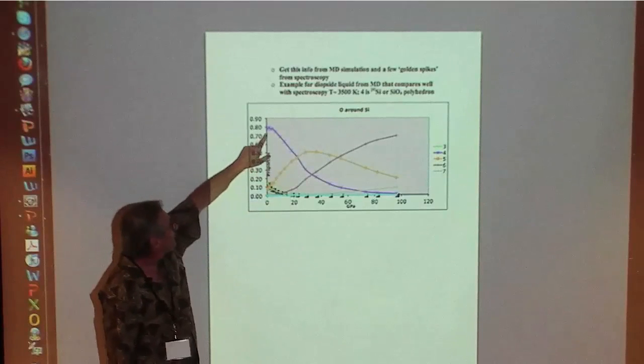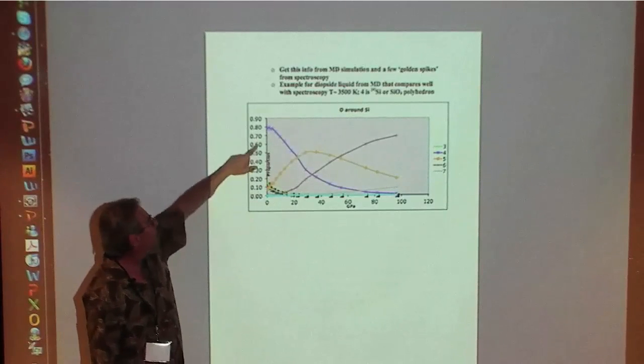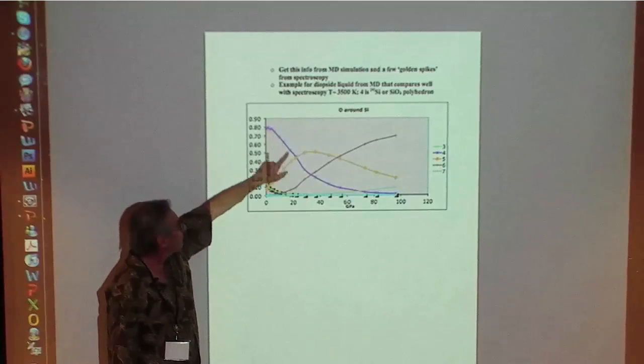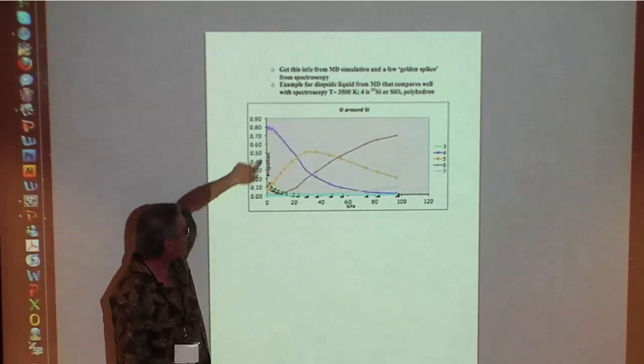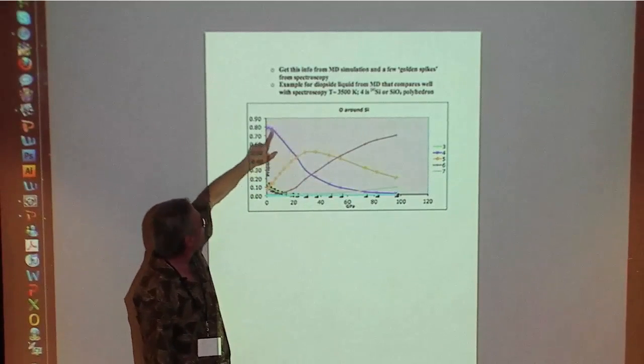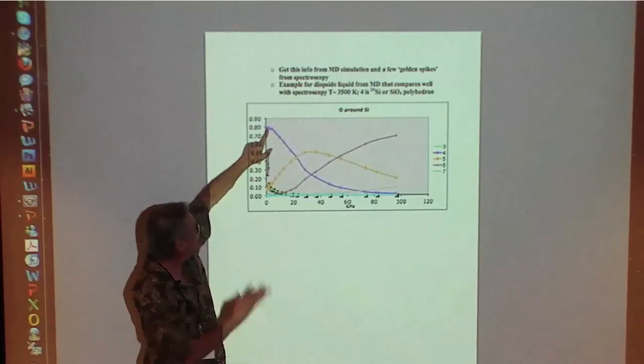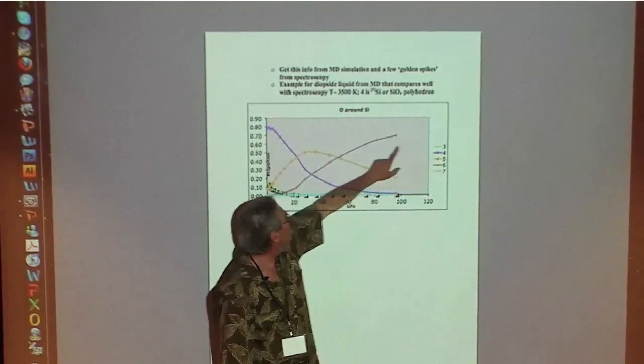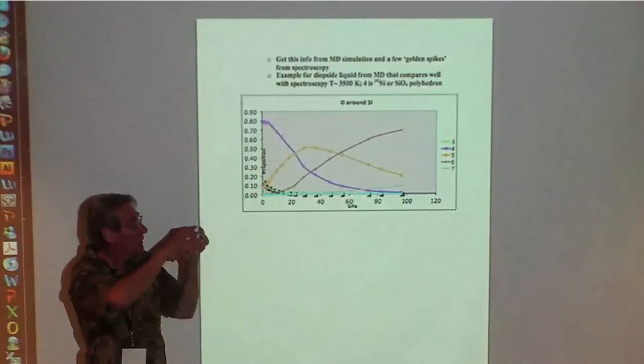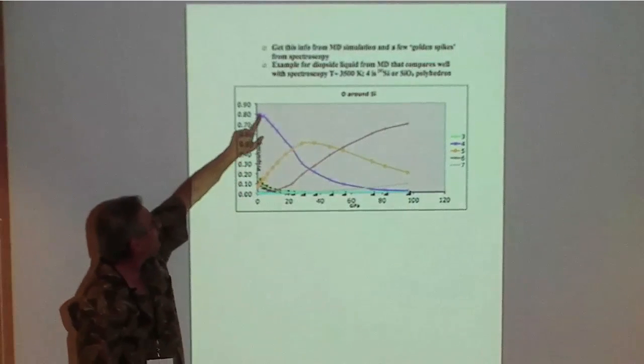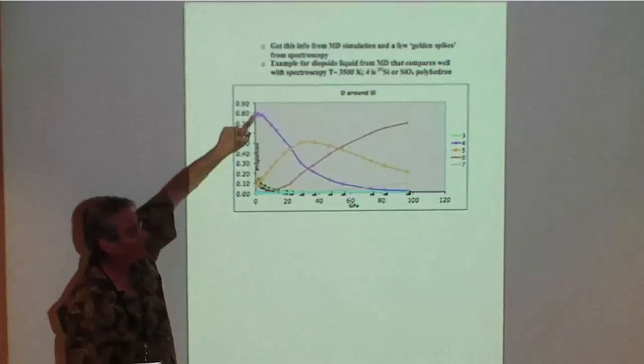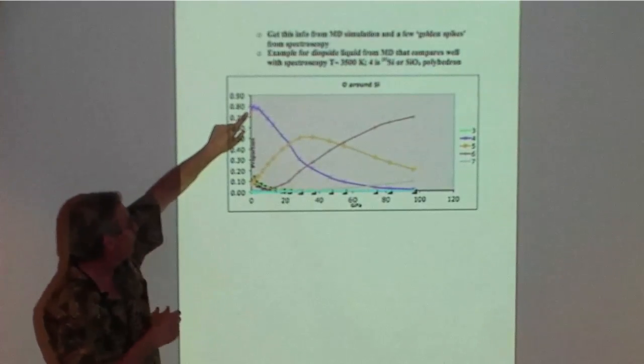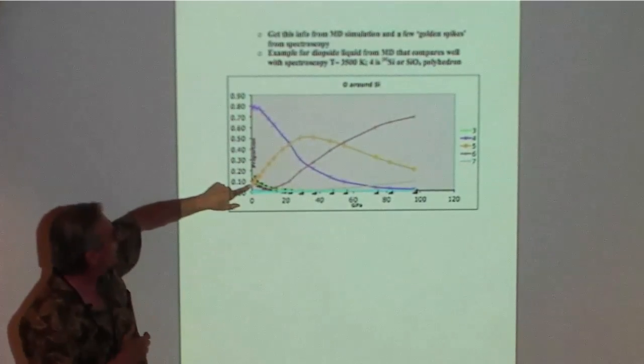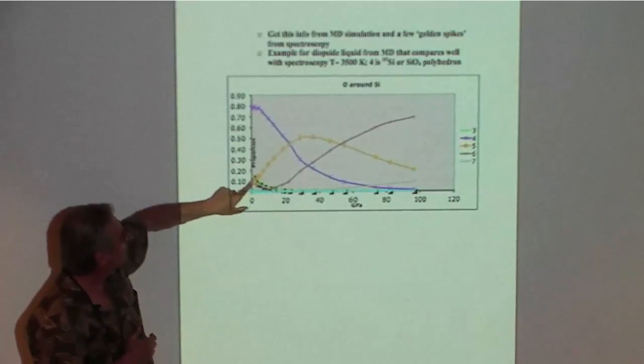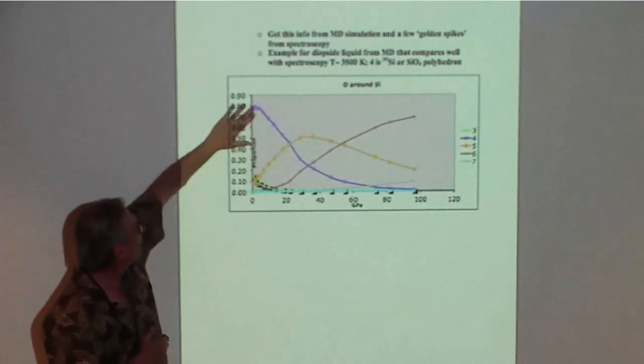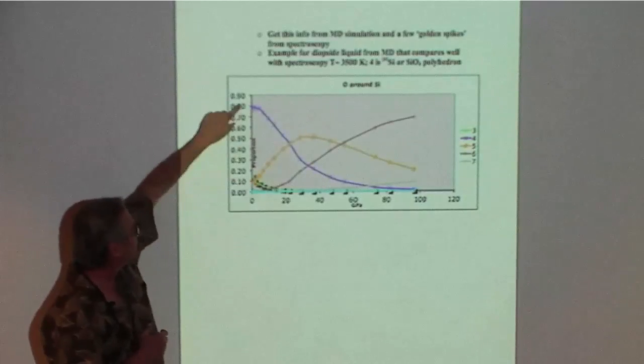Okay. In the liquid, though, notice that this purple curve is the fraction of silicons that have 4 oxygens around. So this is the tetrahedral unit in that liquid. And you see that it's 80%. At low pressures, 80% of the silica tetrahedra are 4-fold. Then you have a few of these. Here's a 5-fold, and a few even 6s maybe. But you're really dominated by these guys. And all these numbers obviously add up to 1.